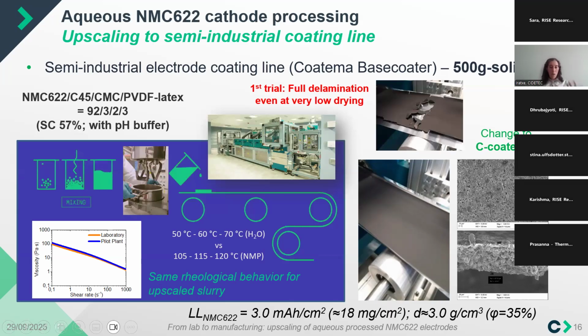In this case, this is what we would expect: the micrographs of a cross-section and surface of a well-defined final electrode produced. At this point, the loading for this particular electrode was 3 milliampere-hour per square centimeter, so slightly below 20 milligrams per square centimeter.